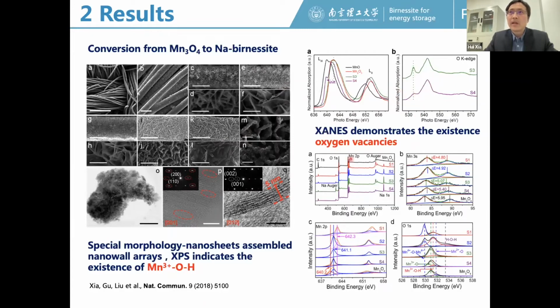And from the XPS result, we speculate there probably exists this manganese-oxygen-hydrogen bond at the interlayer. And we think this may stabilize this layered structure when we remove all the crystal water.